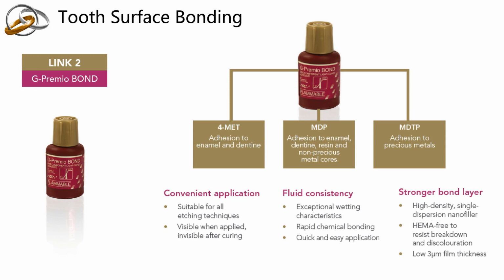Now, the best part of this G Premio Bond is it contains 4-MET, it contains MDP, and it contains MDTP. It provides a great bond strength to the tooth structure, almost 42 megapascals. And another important aspect is that when it is applied onto the tooth surface, it has a film thickness of just 3 microns, which is the least amongst whatever bonding agents are available in the market. 3 microns, and this becomes an ideal film thickness when you're bonding a veneer to the tooth structure.